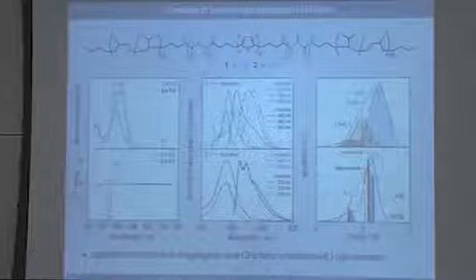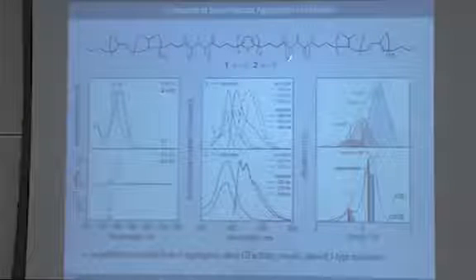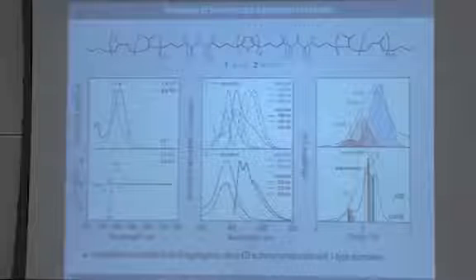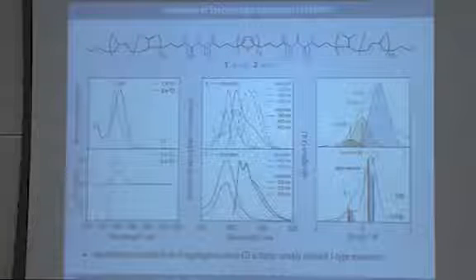As I would like to demonstrate in the following, this tight pi-pi stacking has profound consequences for the question of interaction of the nanowires with light and the question of charge carrier generation. So let's first take a look at the optical spectra of our molecules, both the aggregated ones in solution and non-aggregated molecules, that is, without an oligopeptide, that I will always use as a reference in the following slides. As you can see here, the non-aggregated molecule has a UV-vis absorption peak with a maximum at around 400 nanometers, as is typical for molecularly dispersed quarterthiophenes.